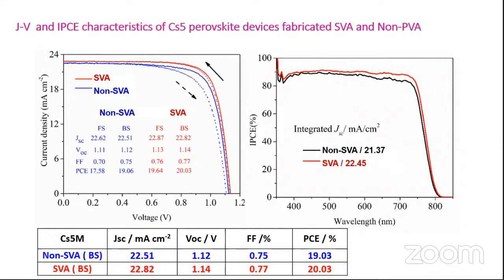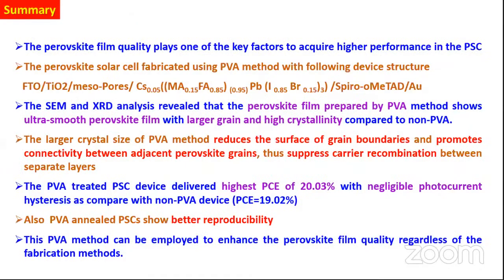From the summary, we can conclude that the SVA method device shows larger grain with ultra smooth perovskite film with high crystallinity. Larger crystals show reduced surface boundary and promote the connectivity between the adjacent perovskite grains. This suppresses charge recombination between the adjacent layers, like the perovskite as well as the ETL and HTL.